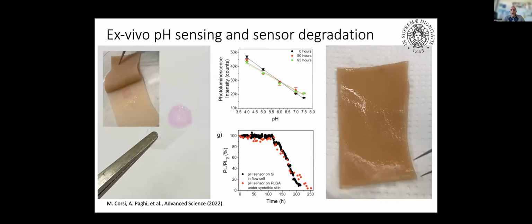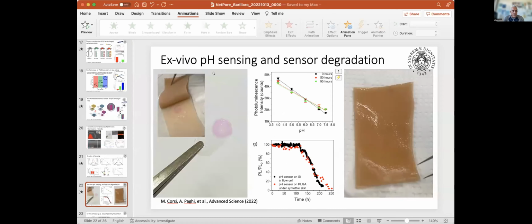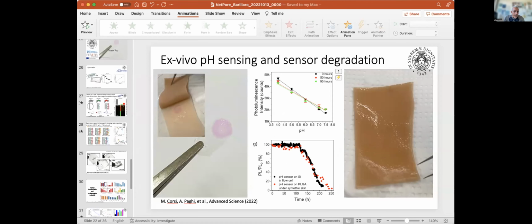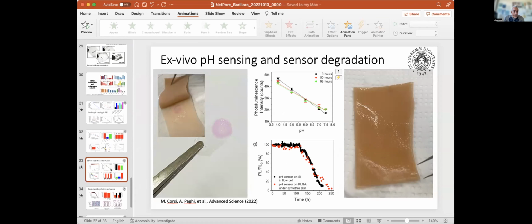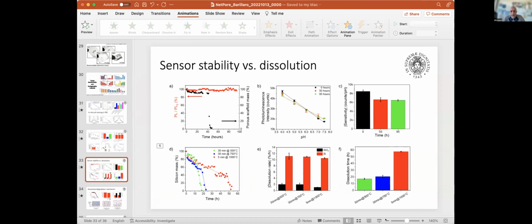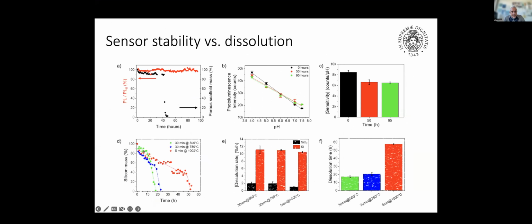No, what we have seen, Ciro, is that the sensor is really reliable. You can cycle the sensor as much as you want. We cycled the sensor for 4 days continuously, and we haven't seen any aging effect. But the limitation here is the degradation of the porous silicon scaffold, basically. I have some backup results depending on the oxidation. We do the oxidation, and depending on the oxidation degree, you see that the scaffold degrades over different times.